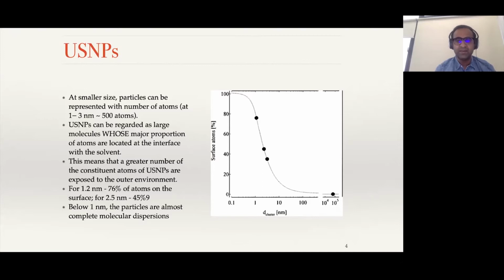So when we say that we are making particles smaller and smaller, effectively we are not letting that particle grow when we are synthesizing. The way you arrest the growth is by using different capping agents, and these capping agents have different surface chemistry. I gave you the example of amines, thiols, carboxylic acid. Now, if predominantly my particle's atoms are present on the surface, let's say I have a 1.2 nanometer gold nanoparticle capped with a thiol, versus a 1.2 nanometer gold particle capped by an amine, they both are going to give me very, very different behavior.